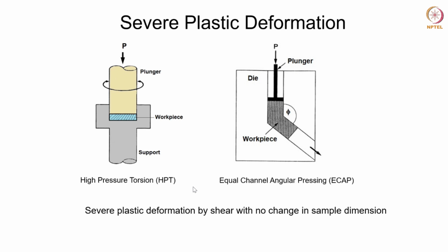There are certain techniques through which this severe deformation or large strains can be generated into the material, and we have listed some of them over here. For example, you can see this high pressure torsion, which also goes by the name HPT in short. This is a torsion kind of deformation that you could see in this diagram. This is the workpiece that you have, which is being deformed in a die, and then it is rotated, and at the same time a vertical load is applied simultaneously on the workpiece. As that occurs, it will lead to a torsion and generate a very high amount of strain into the material, leading to severe plastic deformation, and that would in turn lead to grain refinement.